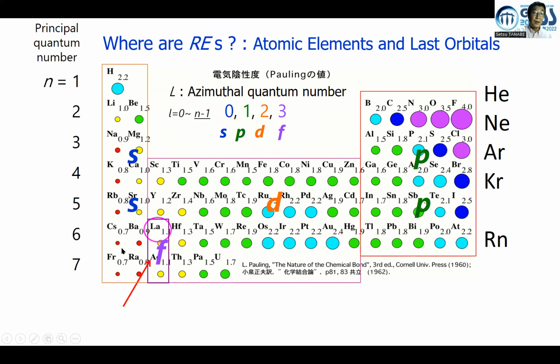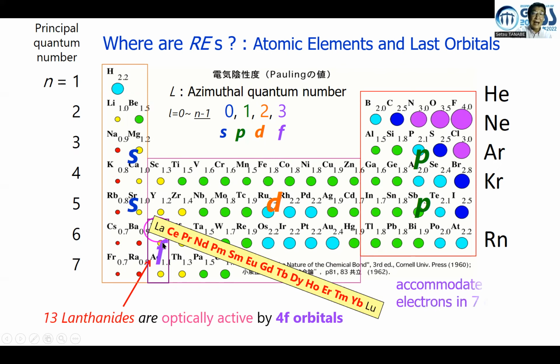Yeah, we can see the s orbital, p orbital, and 10 lines of d orbital, and the f elements are located here, which is not actually the case, but out of the 15 elements, 14 elements are located here after the lanthanum. Among these elements, except lutetium, in which the 7 4f orbitals are fully occupied, the 13 lanthanoid elements from cerium to ytterbium are optically active by the 4f orbital, which accommodates up to 14 electrons.